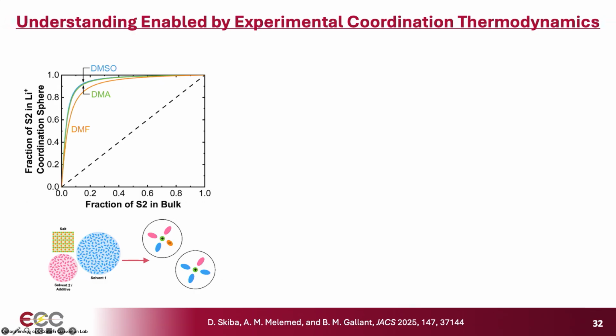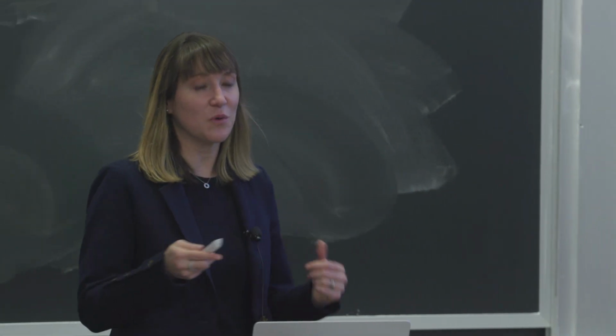So I'll just end this part of the talk by giving you a sense of what this allows us to learn. For example, we can map out, for a particular fraction of a strong solvent in the bulk electrolyte, how much of that is going to go into the coordination sphere, hence be promoted to participate in SEI forming reactions. Right, so this is really powerful. For example, just a small amount of these solvents will actually lead to their disproportionate enrichment in the coordination environment.